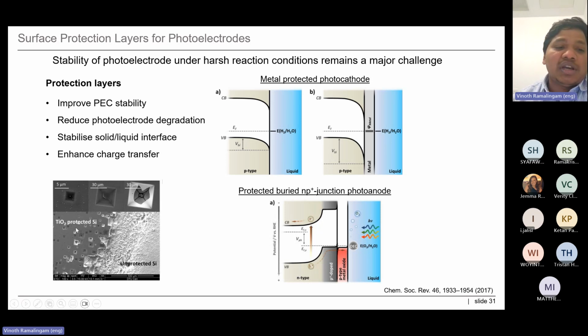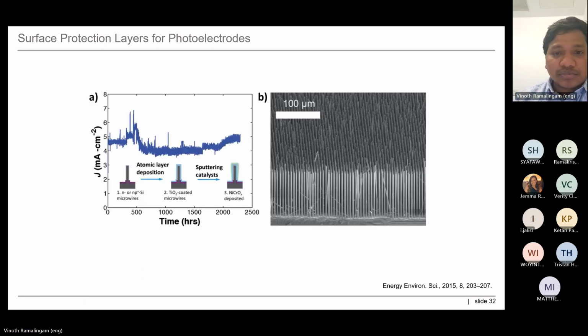Here is an example of TiO2 protected silicon, and this is unprotected silicon. The unprotected silicon degrades very quickly, whereas the TiO2 protected silicon is a somewhat stable structure. There's another example where they used TiO2. They coated a thin layer of TiO2 on the surface of a P plus N silicon photoelectrode. When they coated a thin layer of TiO2, the stability increased a lot. You see, this device can last up to close to 2,500 hours of water splitting reaction, which is good.